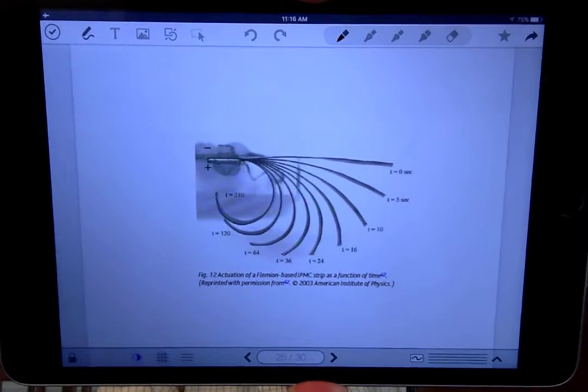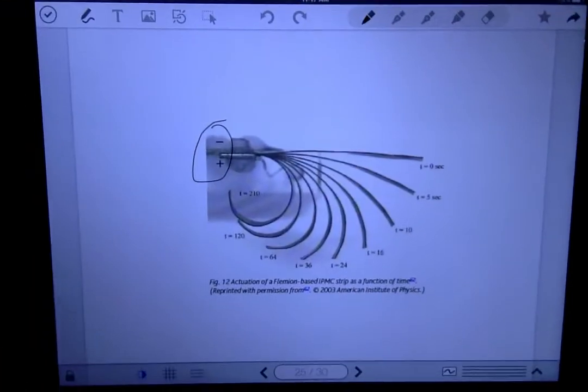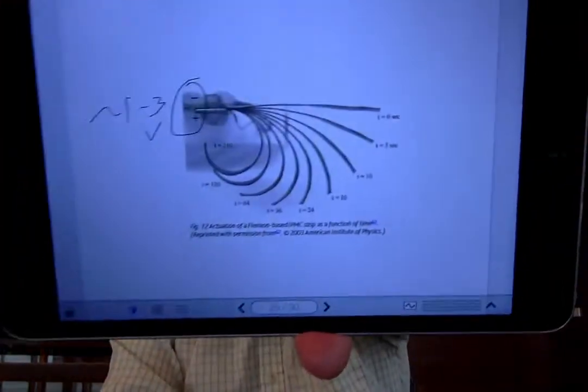From this lecture, you should be able to explain the difference between electrostatic or dielectric actuators and ionic electroactive polymers. These ionic EAPs can undergo high strains — using Nafion with gold leaf electrodes or ionic liquid-filled polymer with nanotube electrodes. The potentials can be pretty low: it doesn't take very many volts to get ions to move. These can respond at one to three volts, whereas PVDF actuators needed hundreds of volts to get dipoles to move. So ionic actuators are interesting because you don't need very high potentials.